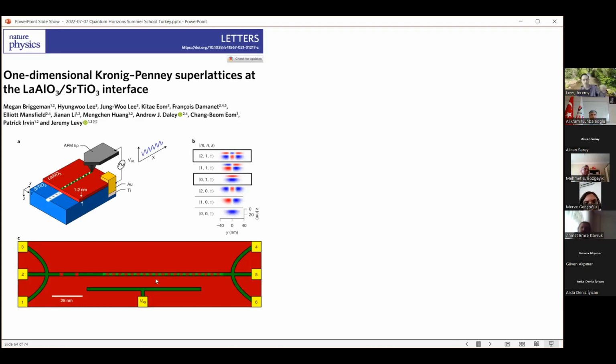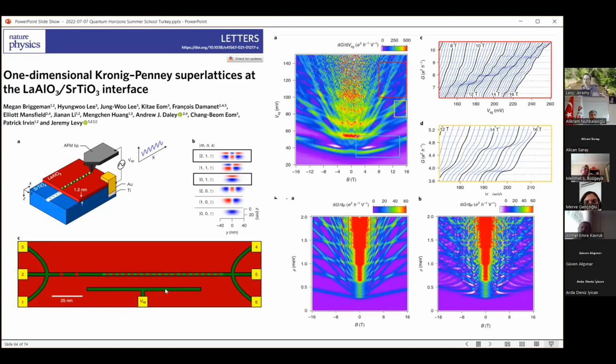One of the things that we did recently was form a Kronig-Penney model. So we start with a quantum wire, and then we modulate it with a period of about 10 nanometers. And what that ends up doing is creating a whole bunch of electronic subbands. And those subbands end up fracturing the electronic bands that you saw previously. Now there's a whole manifold of them that show up, and you get fractional conductances. It's complicated because of the electron interaction.